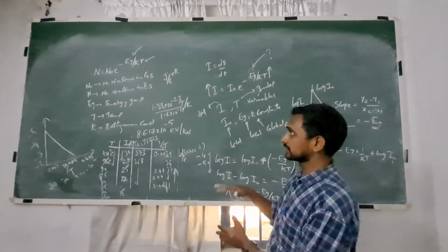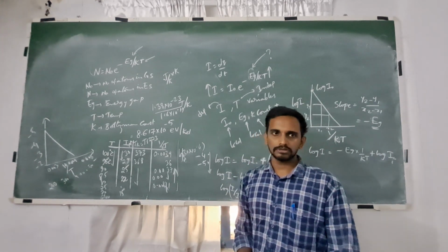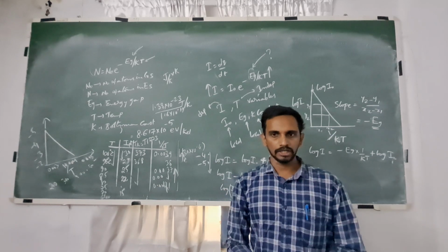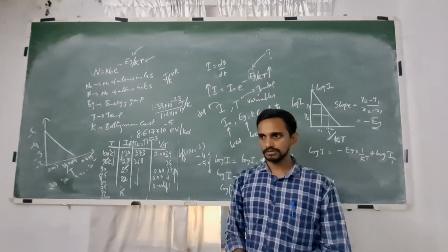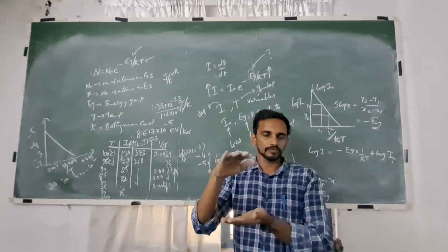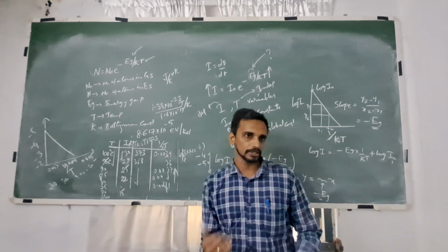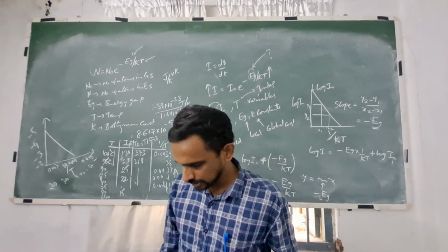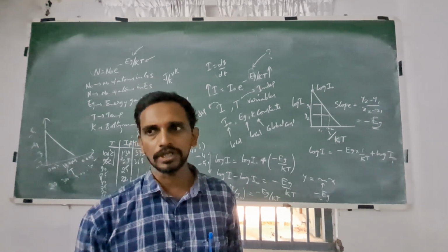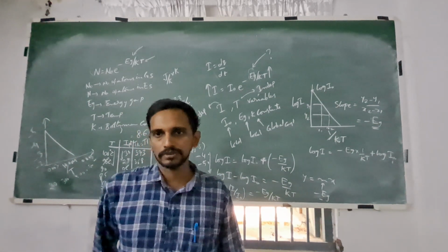So you have to connect the diode in reverse bias configuration, immerse it in an oil chamber, and start heating it. Once you reach a particular temperature above 100, you turn off the heater and then record the current as a function of temperature. Done.